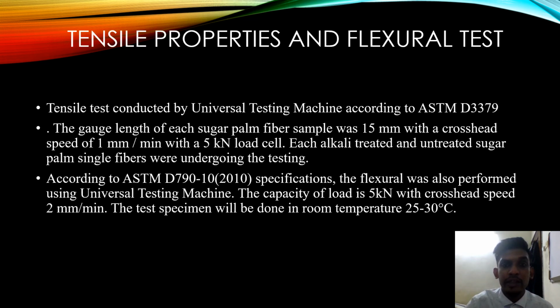Now, tensile properties and flexural tests. The tensile test was conducted by a universal testing machine according to ASTM D3379. The gauge length of each sugar palm fiber sample was 15 mm with a crosshead speed of 1 mm per minute with a 5 kN load cell. Each alkali treated and untreated sugar palm single fiber underwent the test.